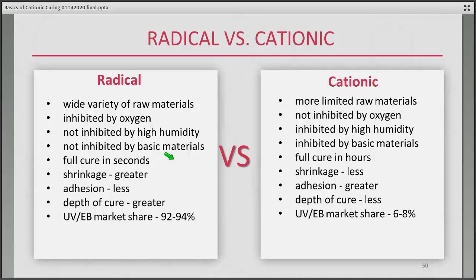Radical curing, you get quite a bit of shrinkage. You can get 10 up to 20% shrinkage, which causes problems, especially with adhesion. Cationic, one of the great advantages of UV curable cationic chemistry is that the adhesion is much better, maybe because for the most part you're using ring opening. You're not losing reaction volume during the photopolymerization, so you don't get the shrinkage. Depth of cure is greater in free radical chemistry, much less in cationic cure, but with the use of anthracene derivatives, you get around that very easily. And overall, radical chemistry probably has in the low 90s market share versus 6, 8, 9% or so for cationic cure. So you have that relative balance there.